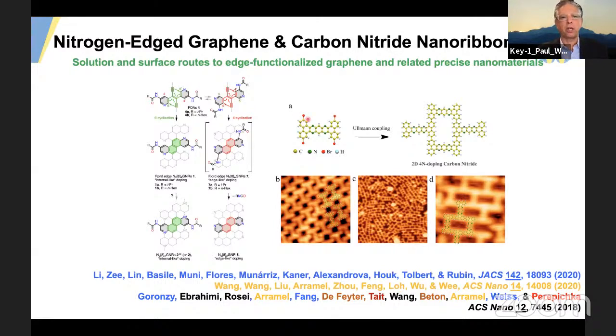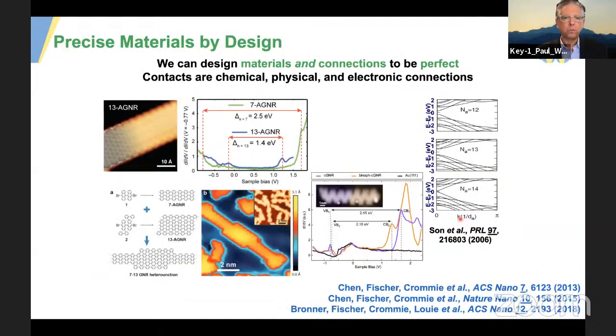So what they've been able to do is put nitrogen on the edges and then use that for assembly as well as manipulation of electronic properties. And the Berkeley group has done these clever surface syntheses in which they vary the width of the armchair graphene nanoribbons to build what is, quote unquote, an inline device, or use side group functionalization in the zigzag graphene nanoribbons in another way to manipulate the band alignment and thereby build an inline device. So there's a lot of creativity that can go into these structures.